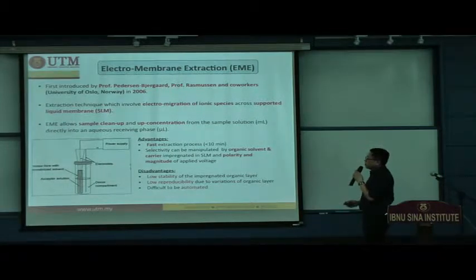This is a typical setup for electro-membrane extraction. This is what we call the hollow fiber membrane. There is a sample solution present in the sample vial, and there is another acceptor solution inside the lumen of the hollow fiber, and the membrane itself is immobilized with a thin layer of organic solvent. The two electrodes are positioned in the sample and acceptor solutions, and voltage is applied to the sample and acceptor solution to create an electrical potential. The ions will then move across the thin organic layer into the acceptor phase.